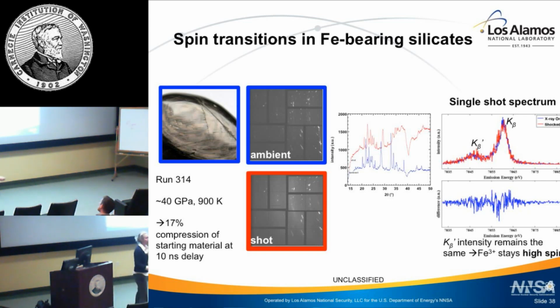Yes, sir? How do you know you have Fe3+ in the sample if the starting material is about? So we did do chemical analysis. There are two sites that we were looking at, where we had Fe2+ and 3+. So that's a good point. It's mixed with this material. I can show you some of the compositional characterization if you'd like. Okay, so now we shock to a little higher pressure.